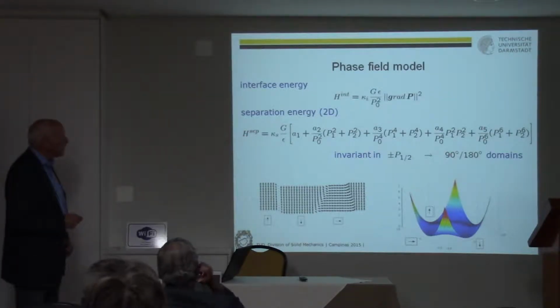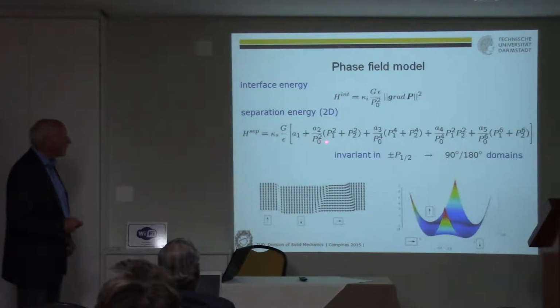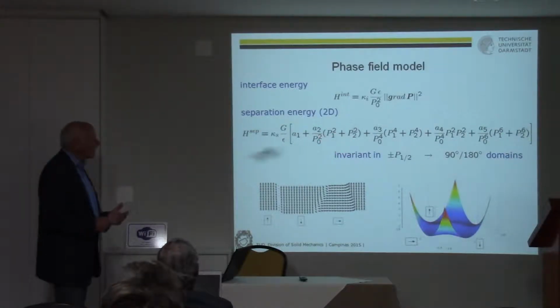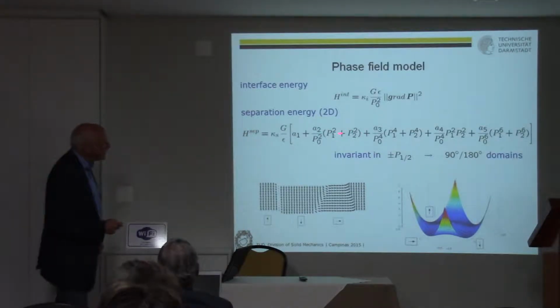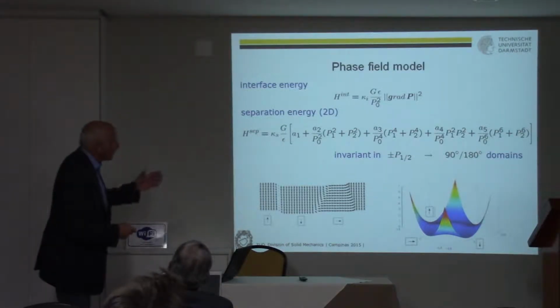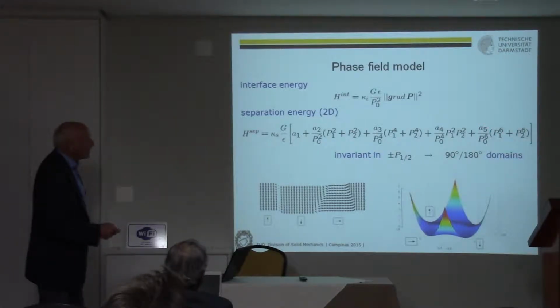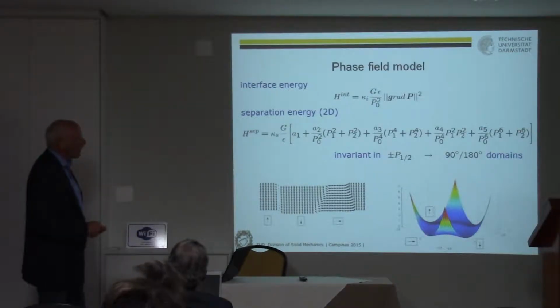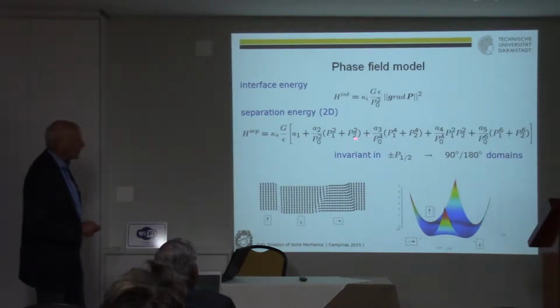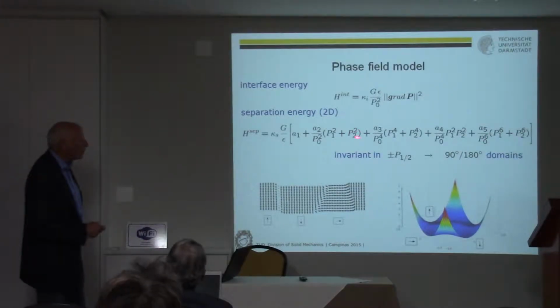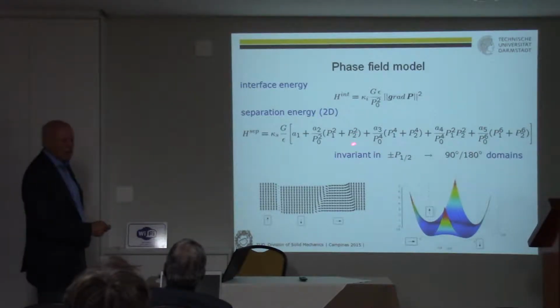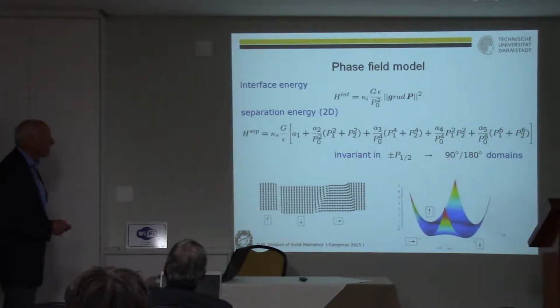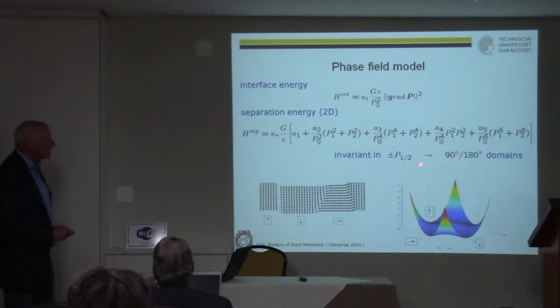And then for the separation energy, this is usual in phase field modeling. You take such a function, say here P squared, then fourth, and so on. You can take, of course, higher orders into account, but then you have a problem with all these constants which appear here, and you have to identify them. And here it's written down only for the plane problem. If you have a 3D problem, then P3 also appears, the third component in the third direction. What you can model with this in 2D simulations are 90 degree and 180 degree domains.